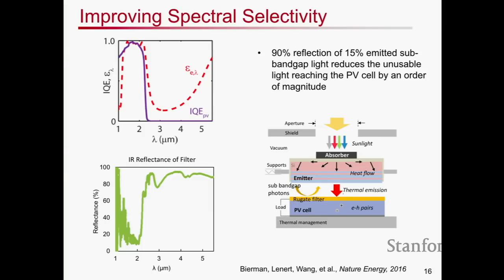I showed you this earlier, this plot of the emission from the one-dimensional photonic crystal design as compared to the band gap of the cell. What I didn't point out, although you probably saw, is that there's still this long tail that can lead to detrimental emission at the lower energies. So the idea here is, can we reflect those low energy photons and then utilize them for emission at the wavelengths that are necessary for the conversion process?